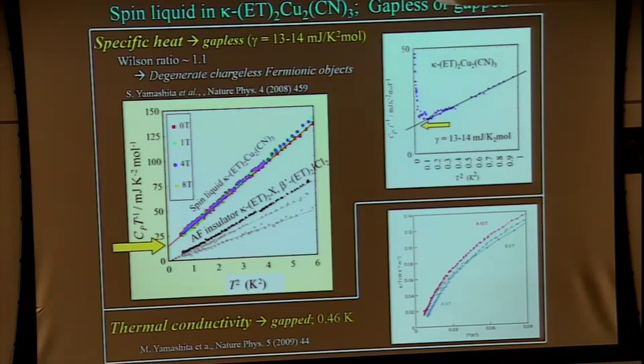The Osaka University group extended the measurements down to very low temperatures, and this is the linear temperature dependence, and then a finite intercept appears. But at the lowest temperatures, they encountered an abrupt enhancement of the specific heat. This is due to the nuclear Schottky contribution, because these materials contain copper ions.